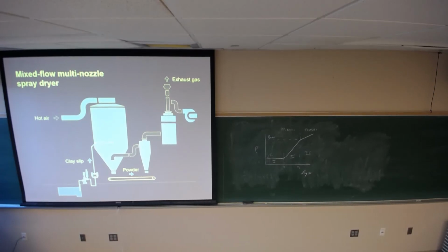And several years ago, about 3 years ago, we were operating this window, and then we started to map statistical experimental design and spray dryer. And found out that we were down in this little corner, and we had all this space that we could increase our volume significantly. What can we do? We could probably do something between 5 and 10 kilograms per hour of material through the spray dryer, as opposed to 1 to 2. These guys, they're doing 10 tons an hour or something like that. Actually, I have numbers. Huge amounts of material going through the spray dryer.